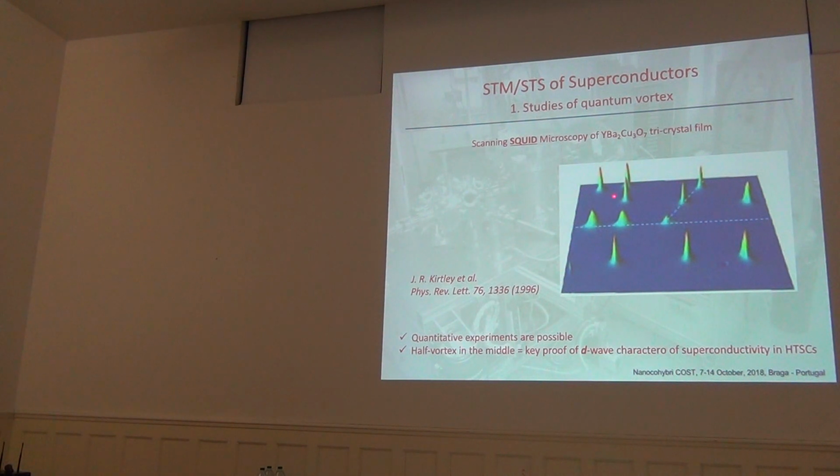You can see that in here there are trapped vortices. Don't look at that, because they are partially Abrikosov-Josephson vortices. But all vortices which sit in each material provide in this SQUID measurement exactly the same amplitude, except this one that sits in the center, and it was a proof that it is not a 2 pi vortex but a pi vortex, so there is half a flux quantum penetrating in.